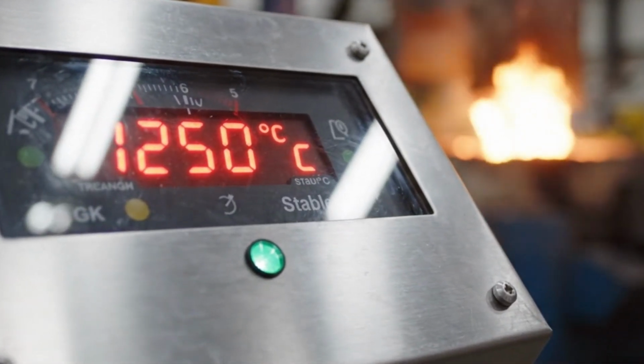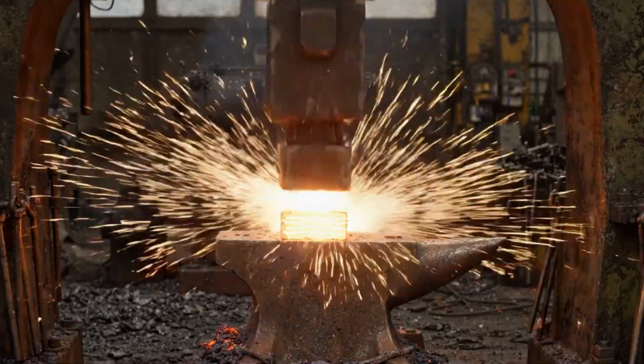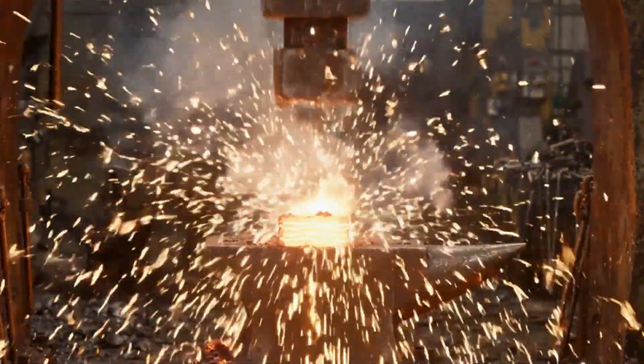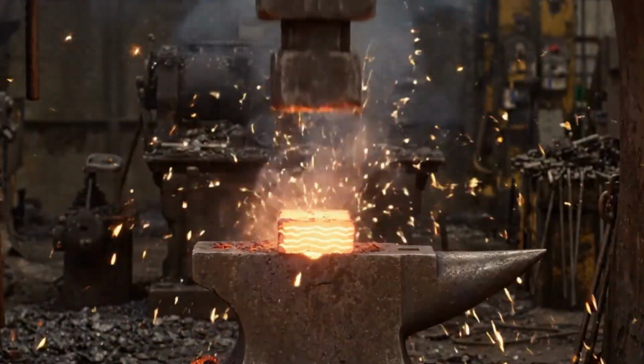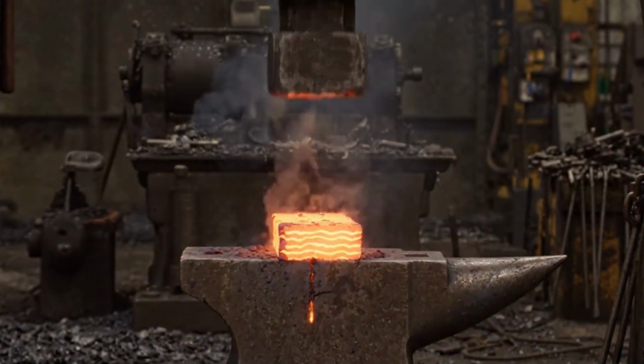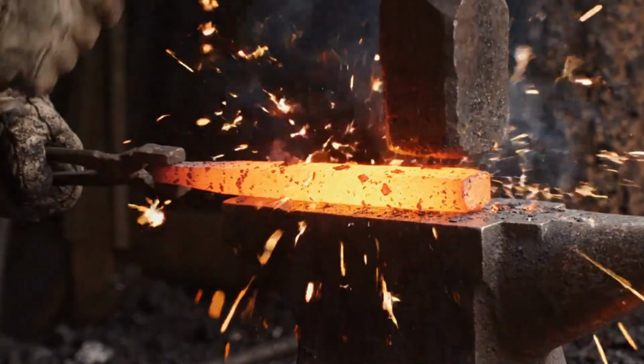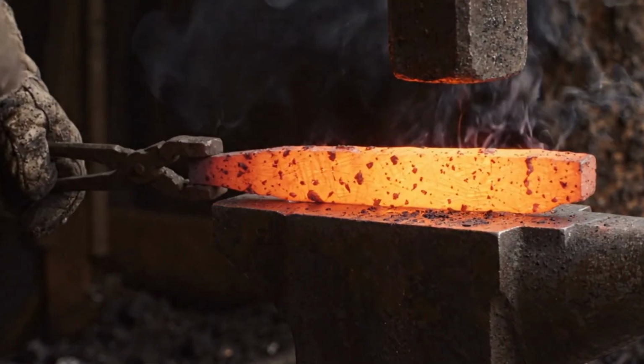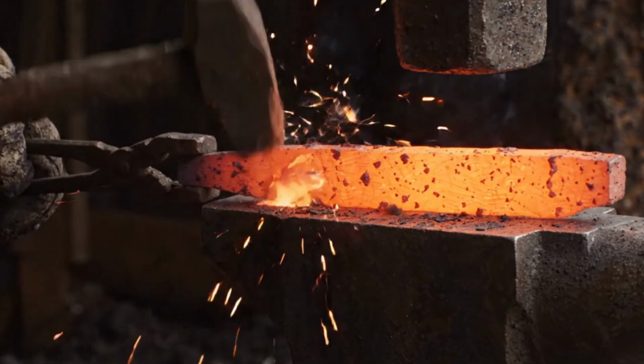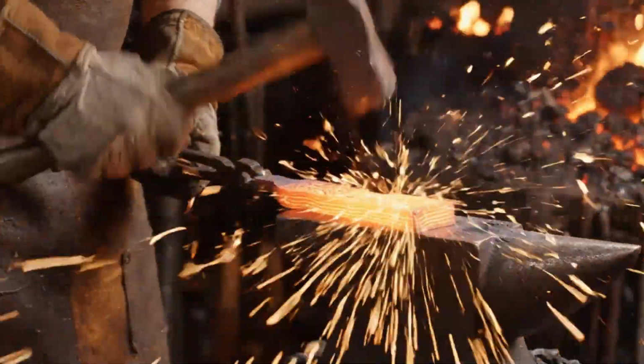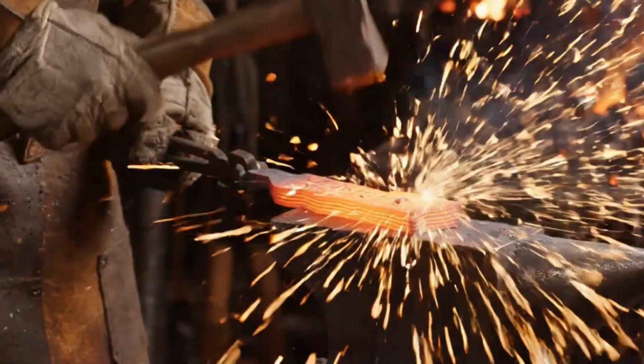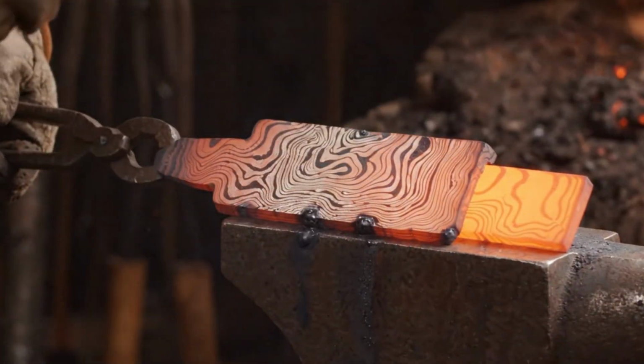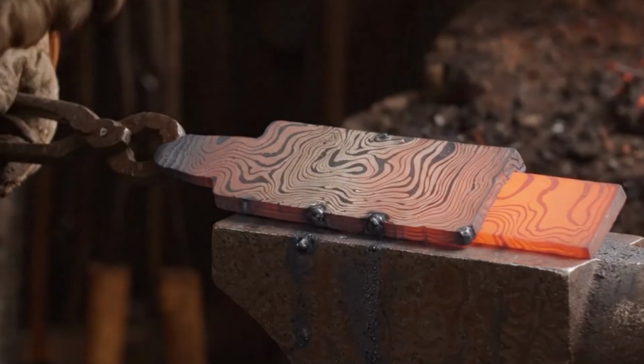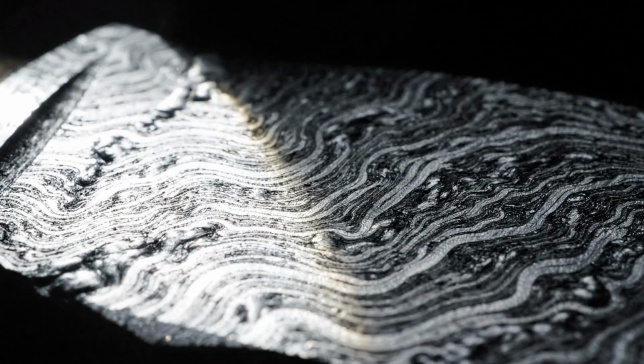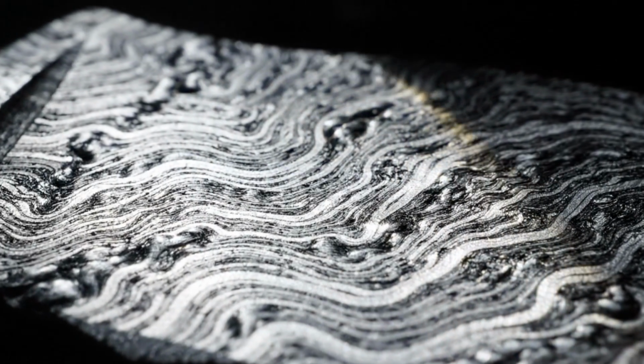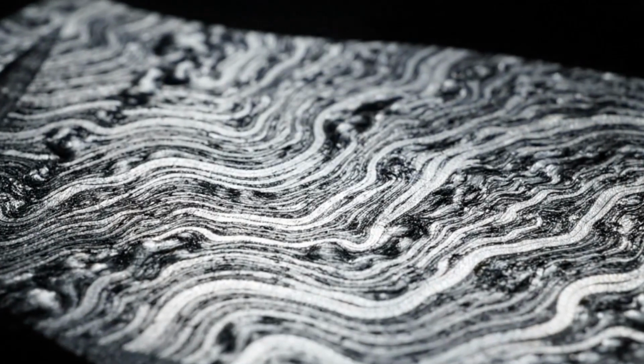Once at the correct temperature, the blacksmith uses a hammer, either by hand or with a power hammer, to compress the layers, forcing them to fuse together. This initial welding creates a solid billet. The billet is then drawn out, meaning it is stretched and elongated, and subsequently folded back on itself. This folding and re-welding process is repeated multiple times. Each fold doubles the number of layers, and with each repetition, the patterns become more intricate and refined. The number of layers can range from a few dozen to several hundred, depending on the desired complexity of the